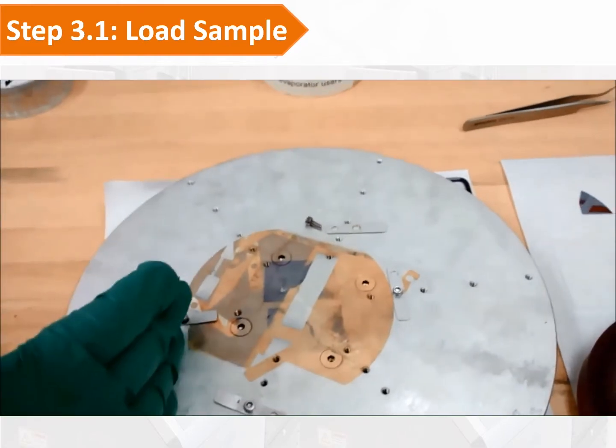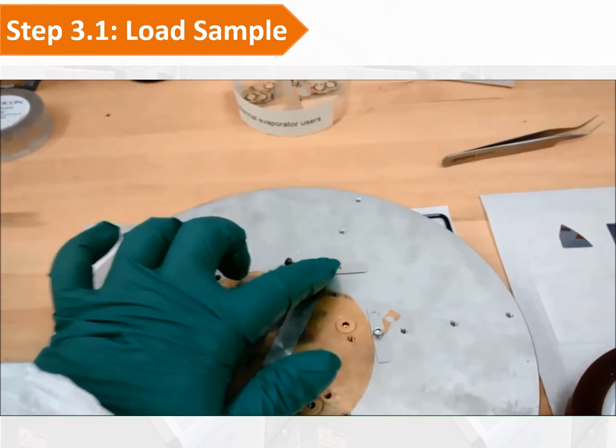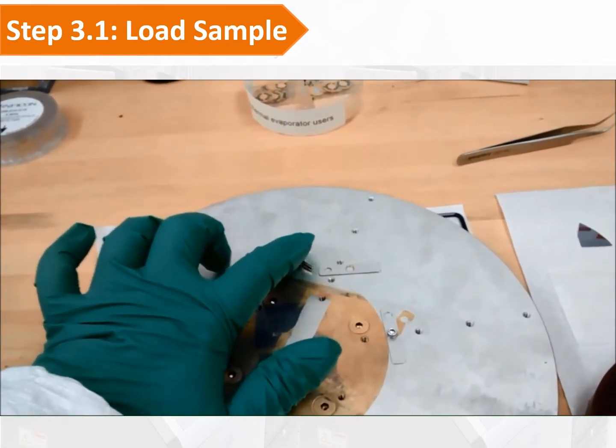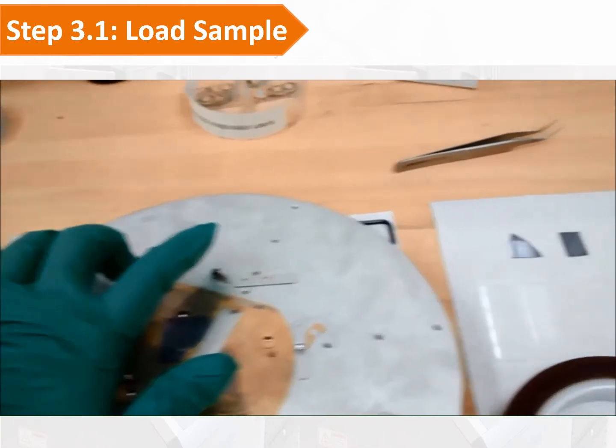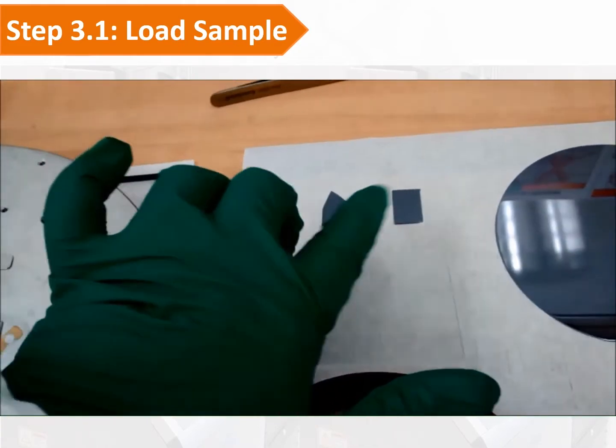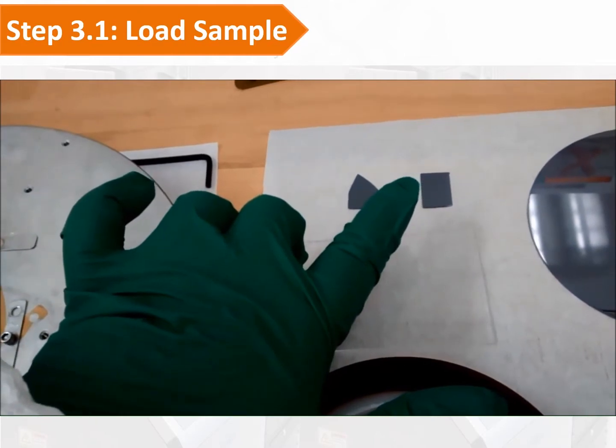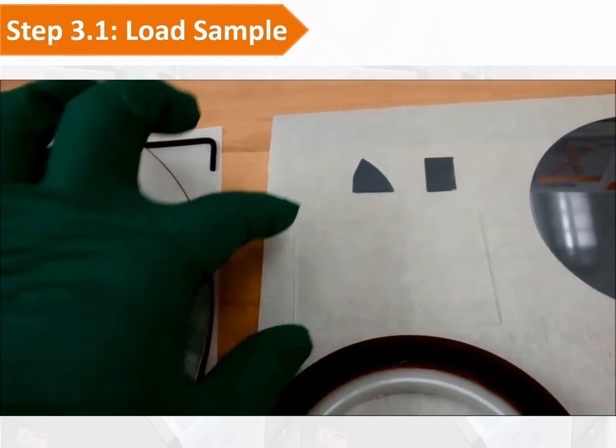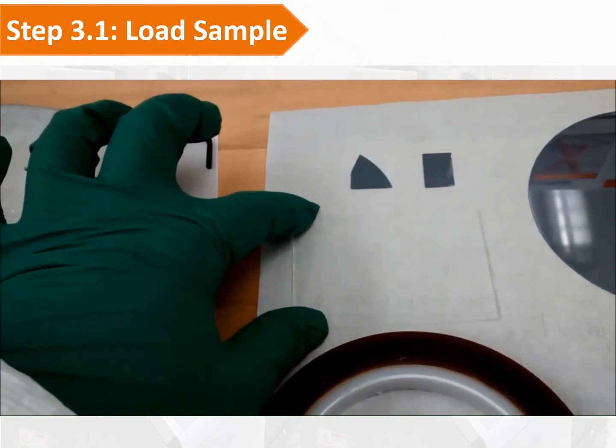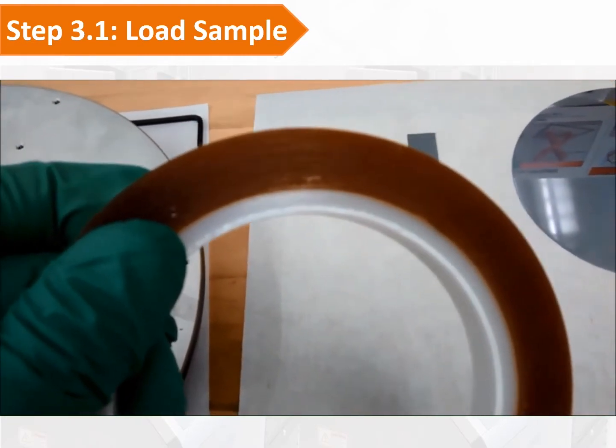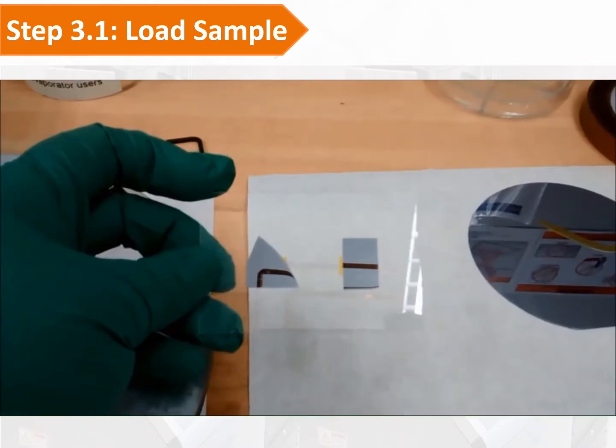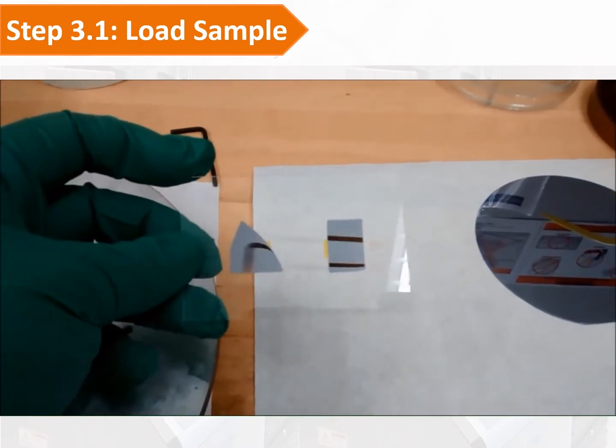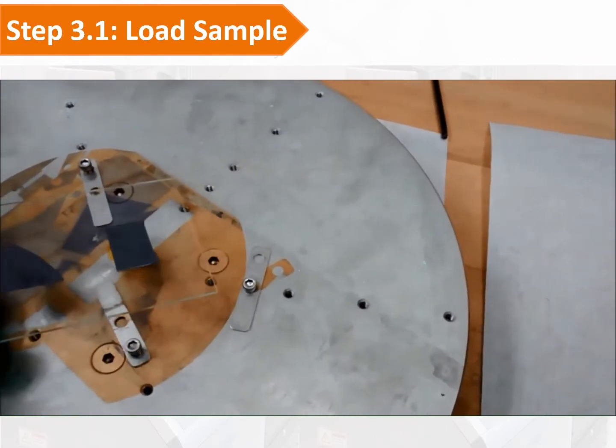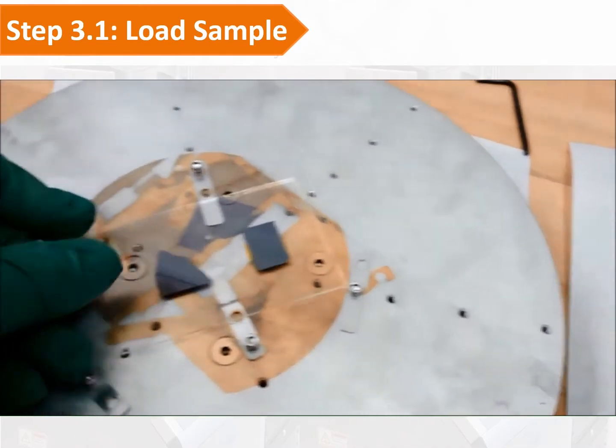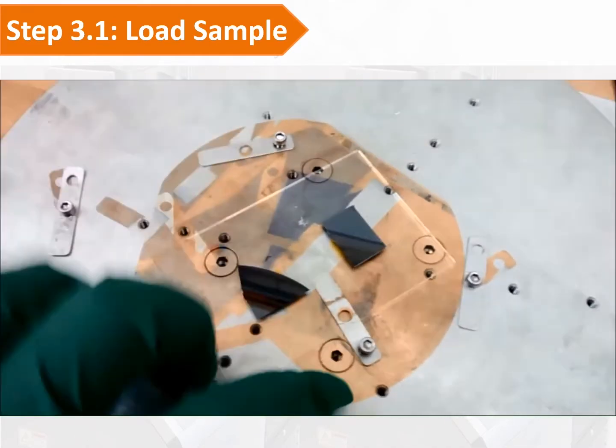And then we need to mount samples. Samples must be mounted to the sample holder using the metal clips and screws. If you have several small samples, you could mount them to a large glass slide using single-sided or double-sided Kapton tape. And this is an example, where we mount the small sample to the glass slide. And then you load this glass slide to the sample holder.